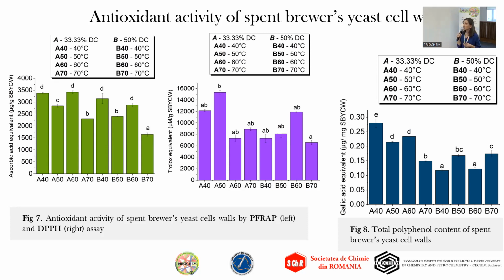And to assess if there are any bioactive compounds such as polyphenols that can be retained during the brewery process on the surface of the cell wall, we performed the total polyphenol content of the spent yeast cell walls. And the highest polyphenol content was obtained when using the optimum conditions, the optimal sample A40, 40 degrees Celsius, 33.3% duty cycle.